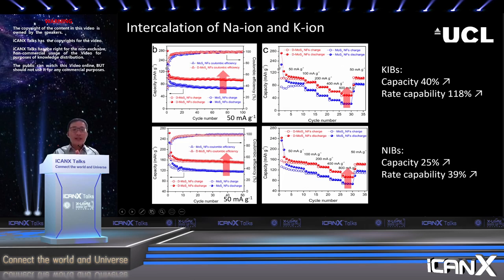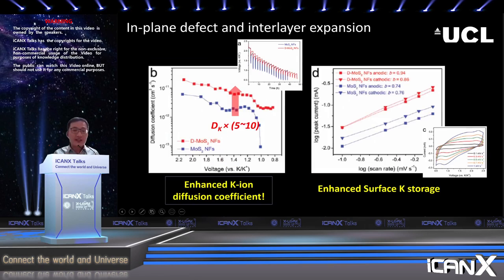So as usual, we try to understand what exactly these defects contribute to the increase of the performance. We calculated the diffusion coefficient of potassium ions, and we observed a 5 to 10 times enhancement of the potassium ion diffusion coefficient. We also characterized the surface charge process of the material, and the results told us that a lot more potassium is actually adsorbed on the surface due to the defects instead of in the interlayer space.